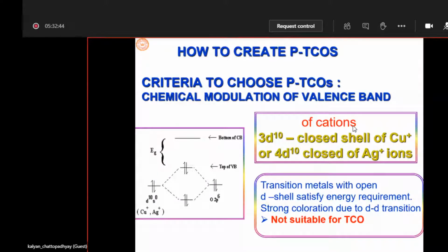But the problem there is some d-d transition, and coloration is produced in the visible part, which is detrimental for transparent devices. So that will not do. So these are the two materials that have to be looked at.